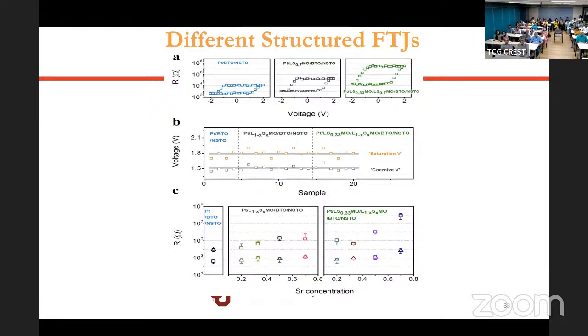It's purely decided by the ferroelectric. So the ferroelectric is the chief that commands, tells you where the switching occurs, okay? So this is a simple thing. What really happens is, if you look at this is the on state, this is the off state. The off state resistance basically changes dramatically as I introduce extra layers, which gives you the very large on-off ratio.